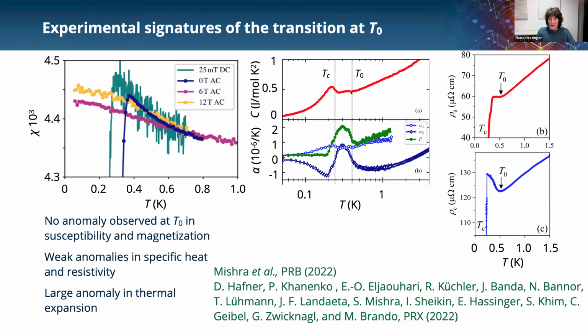And here's again the anomaly in the specific heat, which is small. But then in the thermal expansion, at least along the c-axis, there's a rather pronounced anomaly. So we have clear thermodynamic evidence that there are two phase transitions. And in resistivity, it shows up as an upturn. This is work by Sanu Mishra and co-workers from Philip Ronning's group. And this looks like a charge density wave transition or spin density wave transition.